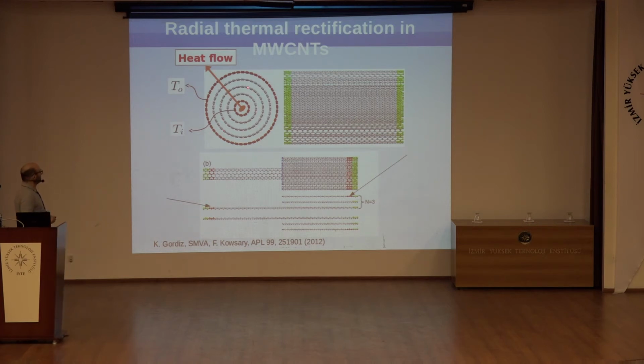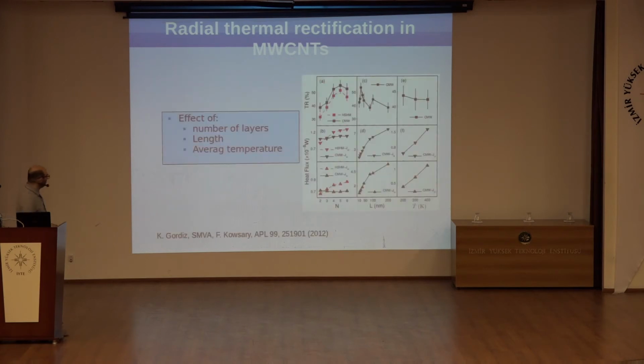For the case of layered media, for instance, carbon nanotubes, it is possible to get thermal rectification if we use hot and cold heat baths at the inner and outer side of the nanotubes. If we connect the inner carbon nanotube to one heat bath and the outer to the opposite heat bath, it is possible to get a considerable amount of thermal rectification. You can see we have almost about 55% of thermal rectification for the case of multiple carbon nanotubes.